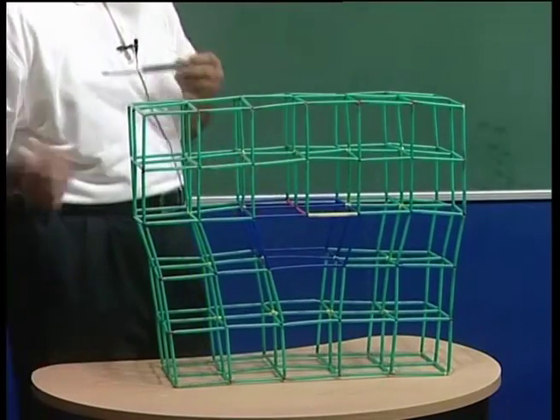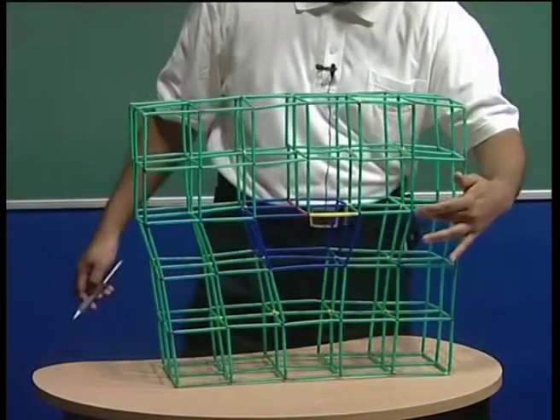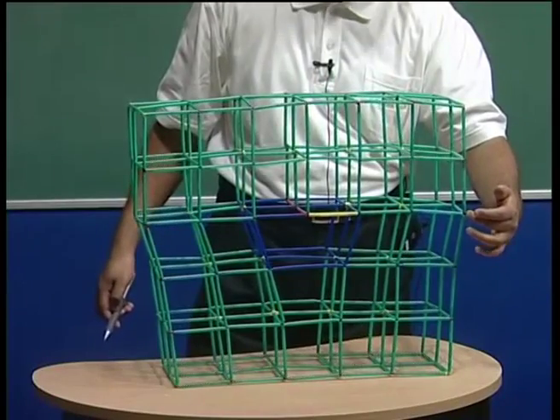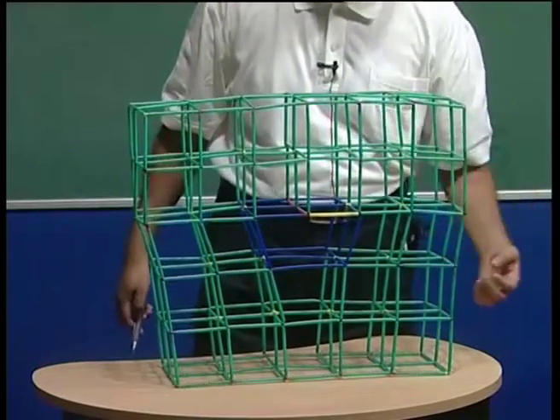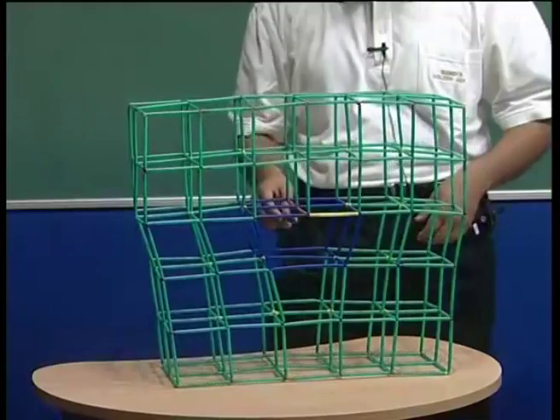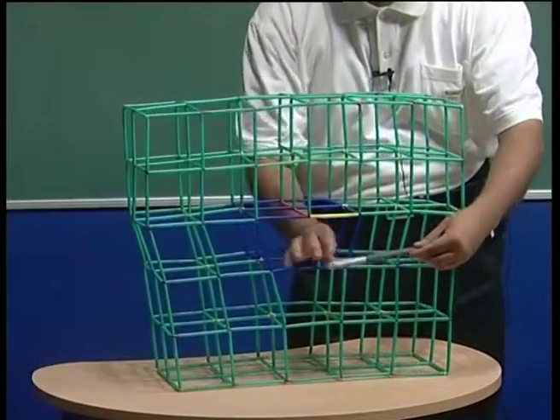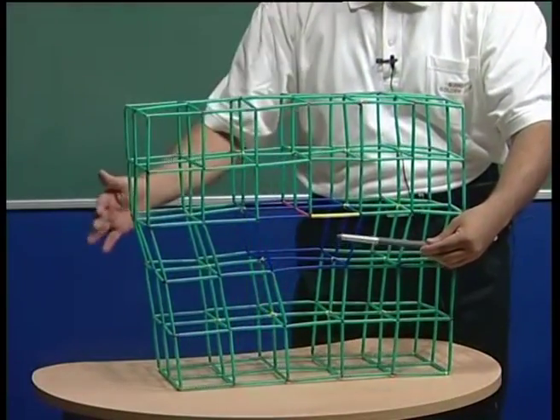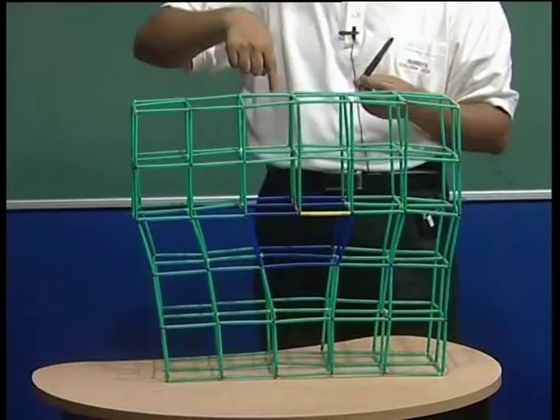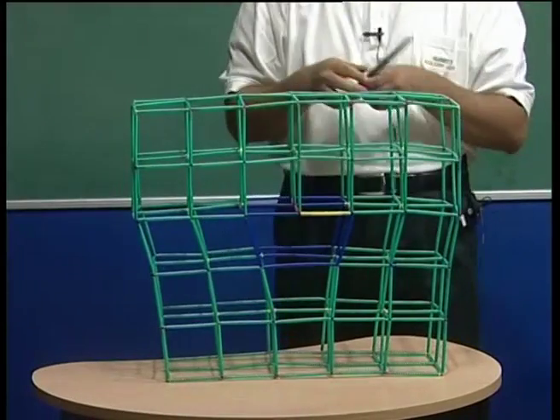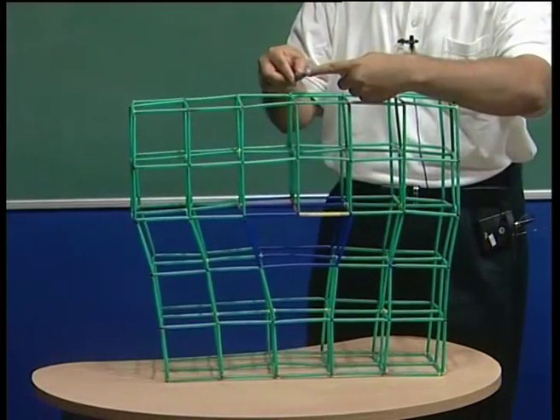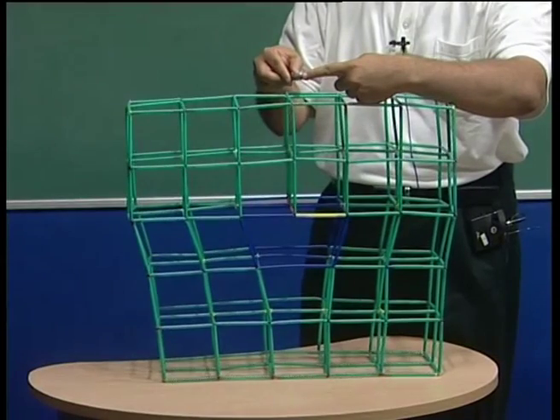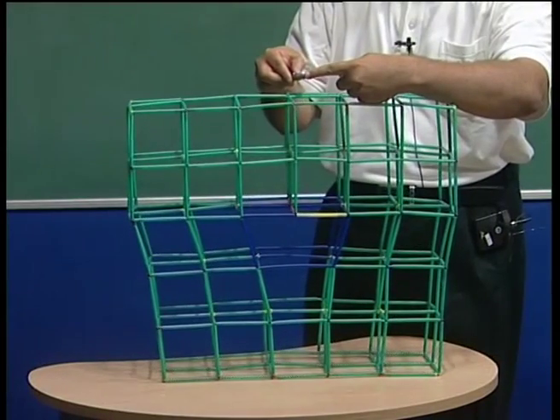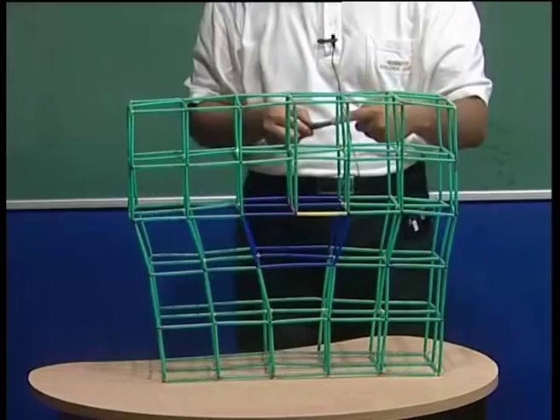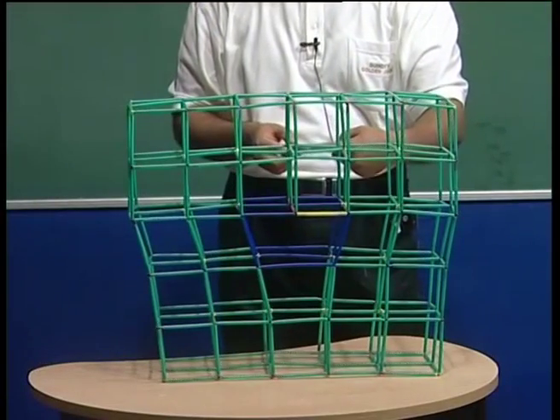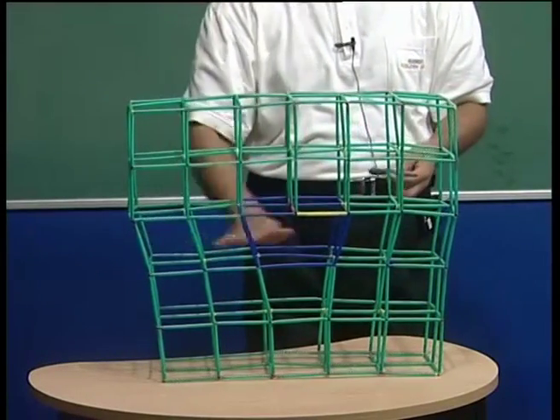Now the Burgers vector is this vector connecting this atomic position to the next atomic position, and this is my B vector. As you can see, the T vector for an edge dislocation, which is this vector, is perpendicular to the B vector. So my T vector is in this direction, the B vector is in this direction, and the T and B vectors are perpendicular to each other. So this is an important point to be noted, and the T vector and the B vector together define my slip plane.